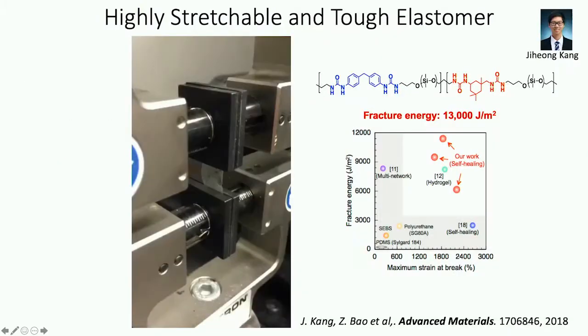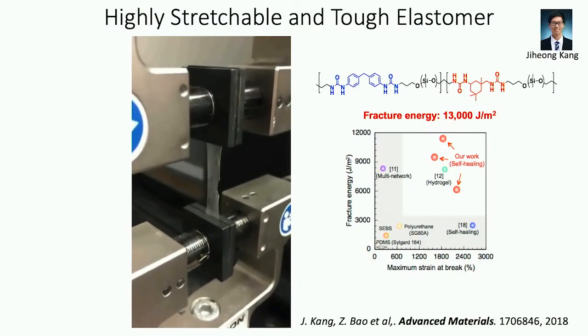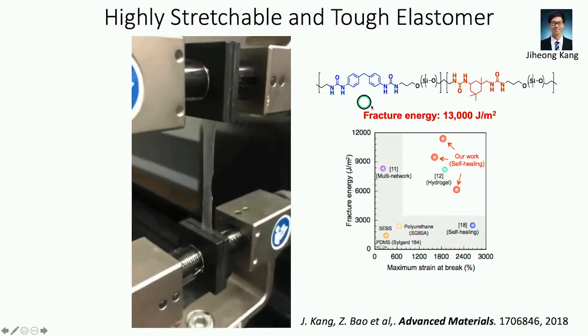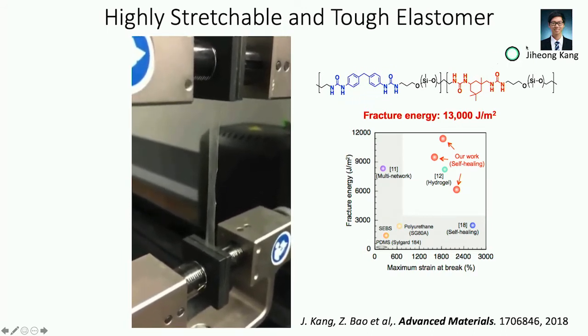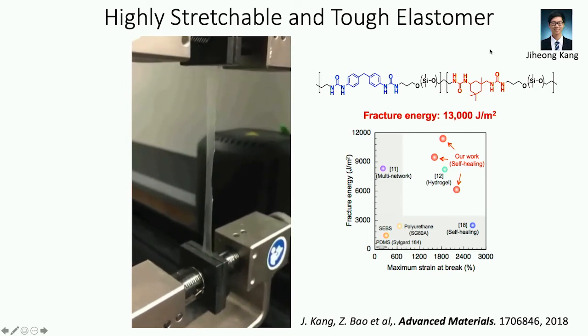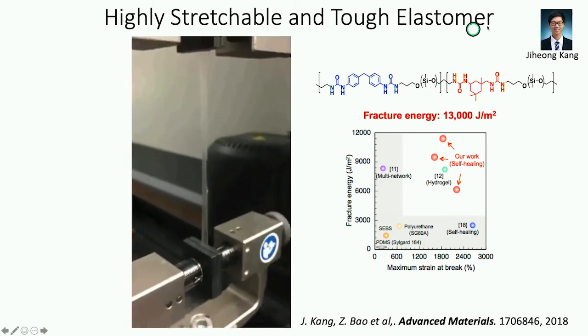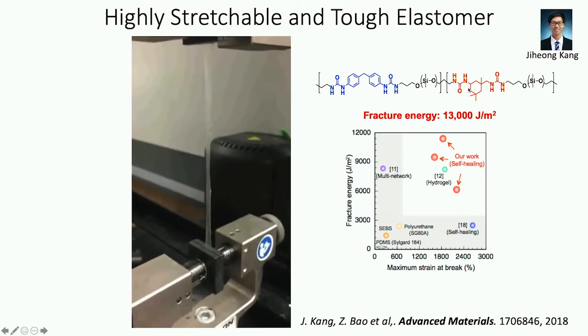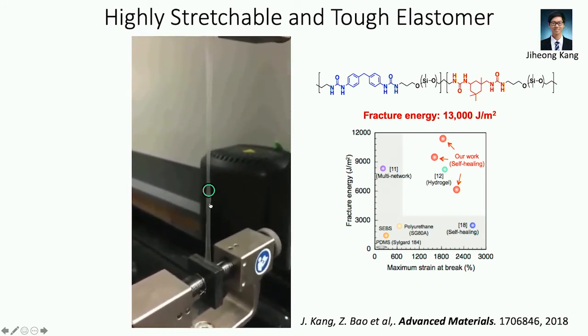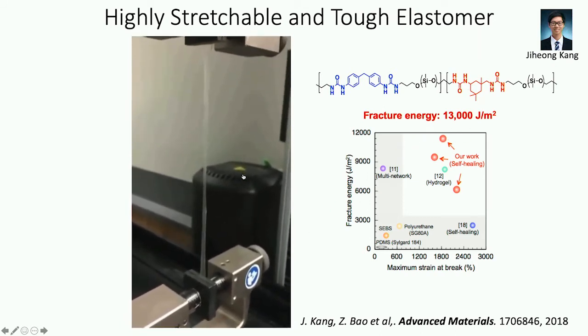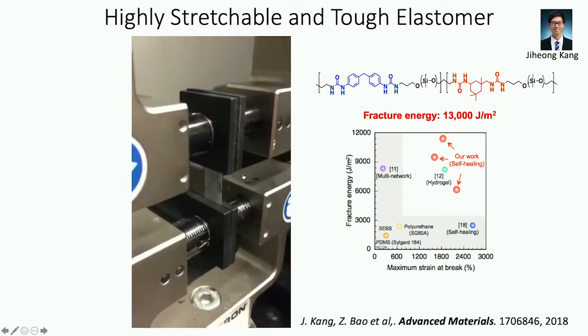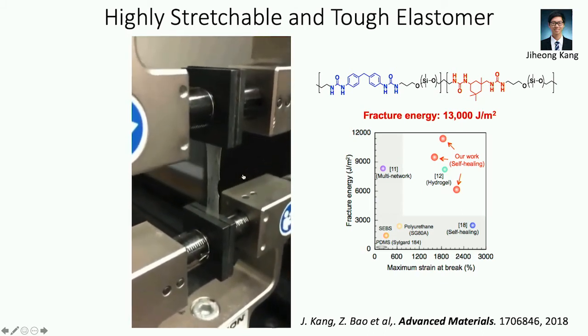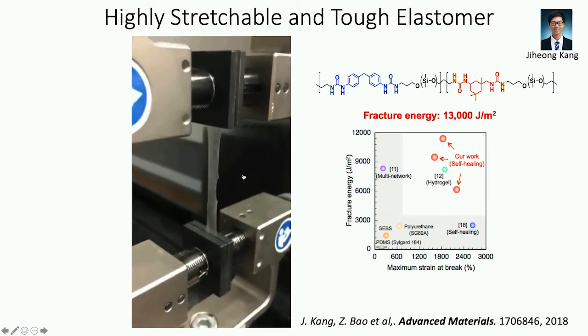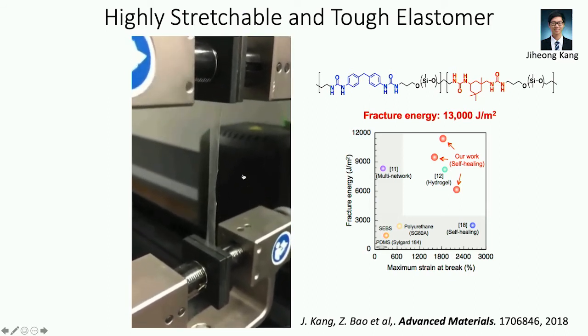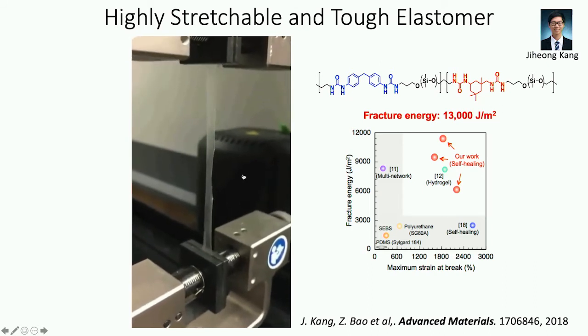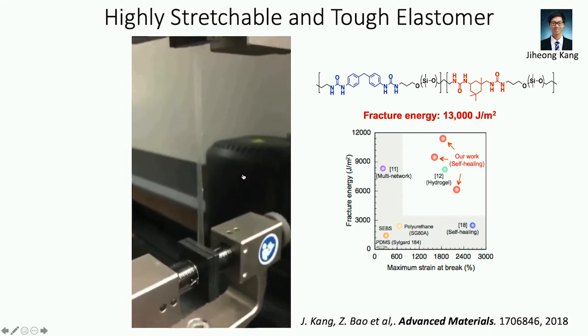So the best design that we found is actually a combination of, as I mentioned, the stronger hydrogen bonding and the weaker hydrogen bonding. And when we tune these bonds to be just the right ratio, we can have a material that is not only elastic, but even if you intentionally introduce a defect, it can still be stretched under very large strain without having the crack propagate along the defective sites.